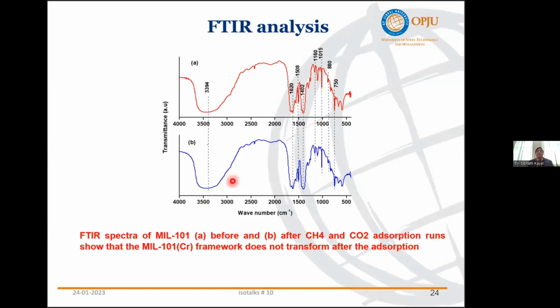And you can see all their corresponding peaks. This 3394 peak and the one around 1620 are due to the stretching and bending vibrations of adsorbed water molecules. And this 1402 is basically OCO from the dicarboxylate. We have used benzene dicarboxylic acid as the organic ligand, and this peak comes from there. And the peaks from 600 to 1600 all correspond to the benzene ring, because benzene dicarboxylic acid has a benzene ring. So 1508 is due to C=C vibration.